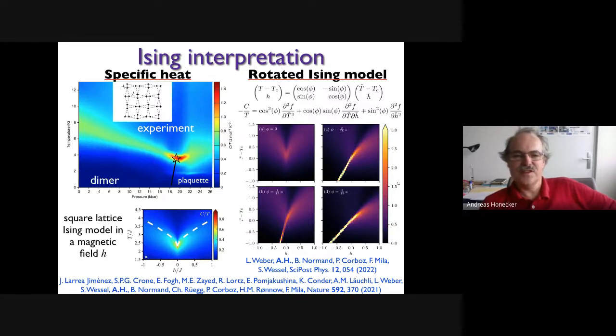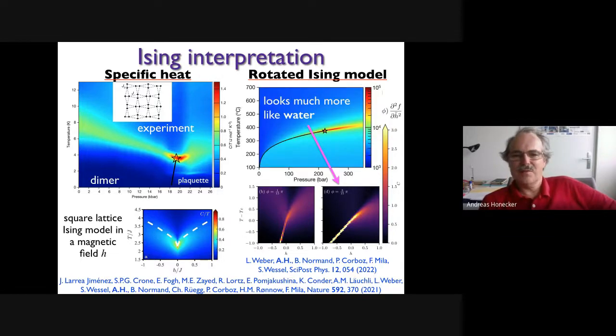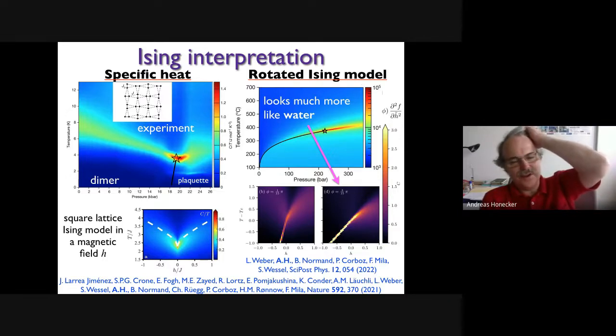And doing this mixing, you do an increasing rotation. And so you see the specific heat plot changing as a function of rotation angle. The upper left plot is exactly this square lattice Ising model. But if you have rotated this to the bottom right, then it actually does look exactly like what you get in water. So what we really do believe is that these two kinds of physics are really the same physics. So if you wish, this phase diagram of water is 200 years old, and now you have actually in a quantum system exactly the same phase diagram, except at lower temperatures and in a very different parameter regime. And the difference here is essentially how mainly pressure is related to an effective field.